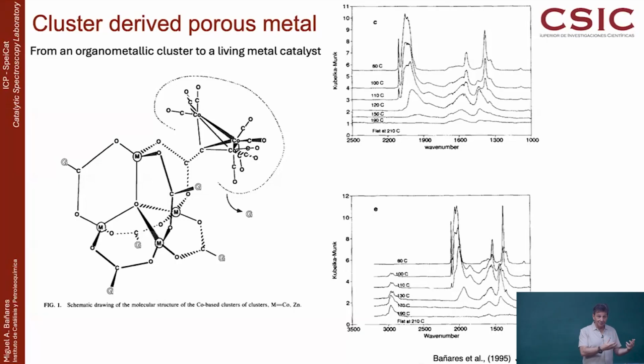organometallic compound. The organometallic compound is no longer there, it's becoming like a metal, and the few ligands that remain start behaving like chemisorbed CO. And at the same time, because we were feeding propylene, butadiene, you start to observe the adsorption of the hydrocarbons, how they are being adsorbed at the surface of the material, and you start to observe hydrogenation products. So you see the birth of a catalyst through the decomposition of an organometallic compound.